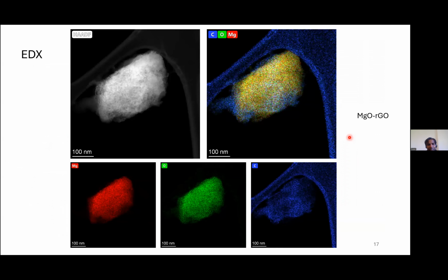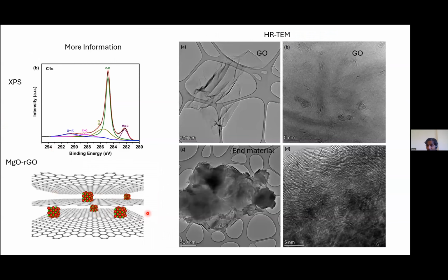And then one another investigation is scanning, chemical scanning in high resolution. Our interest is to know how well localized these ingredients of this structure are: magnesium, oxygen, and carbon. You see, very well localized. There are no separate patches or islands. That clearly suggests that this material can be a very composed version, an atomic level composed version of something. That could be something like this, or something closer to that. This is what we were looking for.